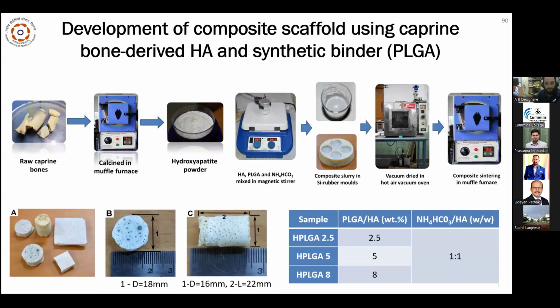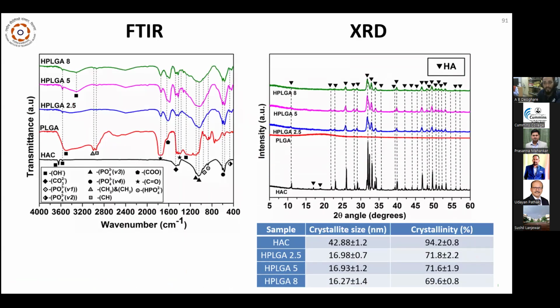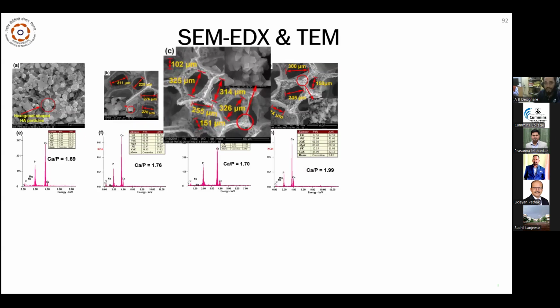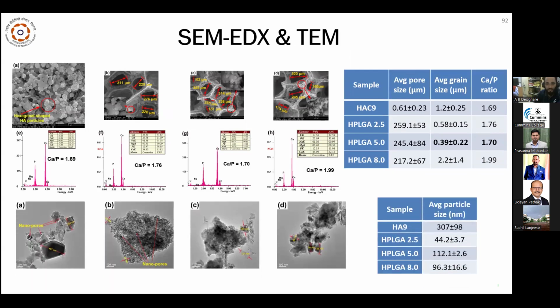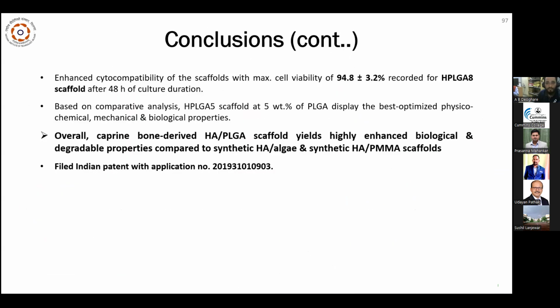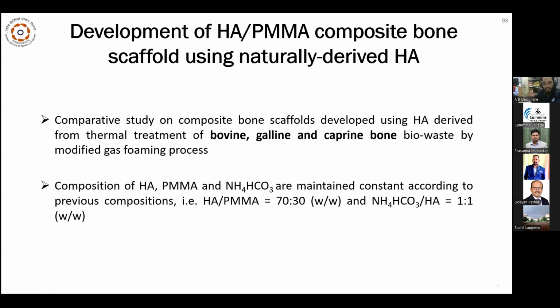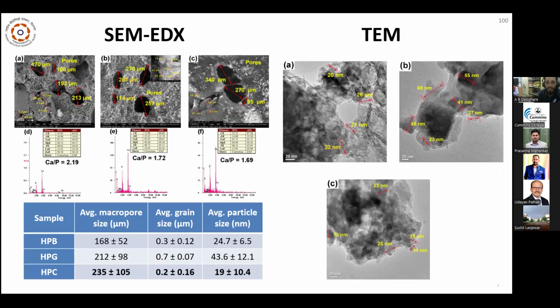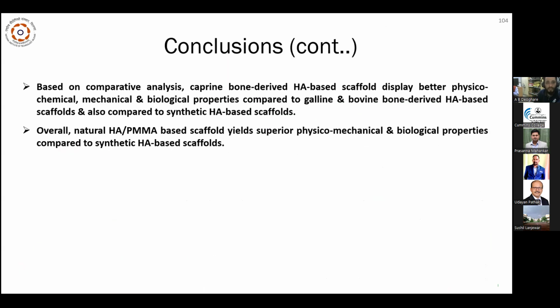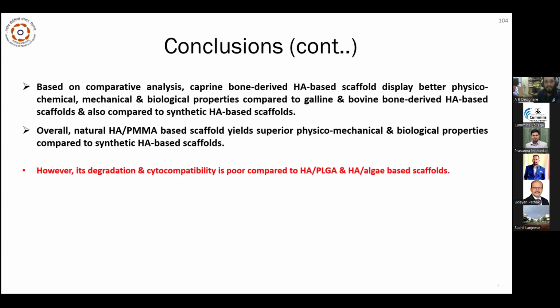This is the flow chart for the preparation of the developed scaffold, where the synthesis process is almost similar to what was discussed previously, and then different characterizations are performed: FTIR, XRD, SEM, and EDX, and they show a porous structure. However, from the above analysis, it is observed that the mechanical strength is poor compared to the synthetic hydroxyapatite and PMMA scaffold. Then all the characterizations are performed, and it is observed that the caprine bone derived hydroxyapatite scaffold displays better chemical, mechanical, and biological results compared to the galline and bovine bone derived hydroxyapatite scaffolds. However, the degradation and cytocompatibility are poor.